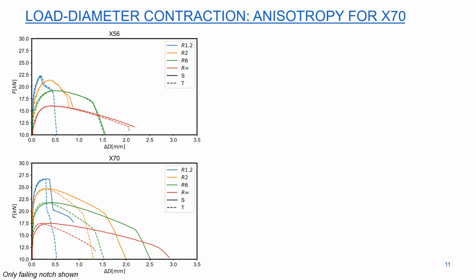By analyzing the pictures and correlating them with the force, the diameter contraction in both the transverse and thickness direction can be evaluated. Interesting here is the difference between the T direction, the dotted line, and the S direction, the full line. For the X56 steel, there is little difference between the two. For the X70 steel, a large difference can be observed. This indicates the presence of plastic anisotropy in the X70 steel.